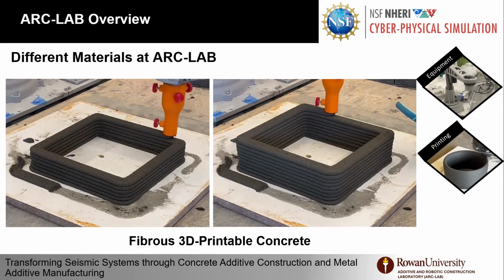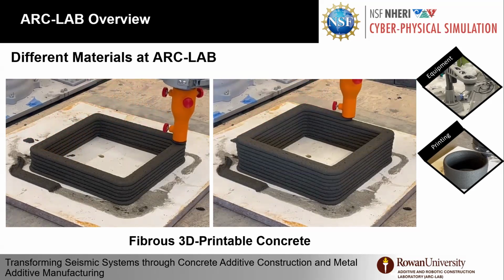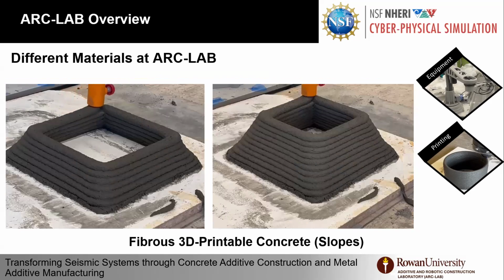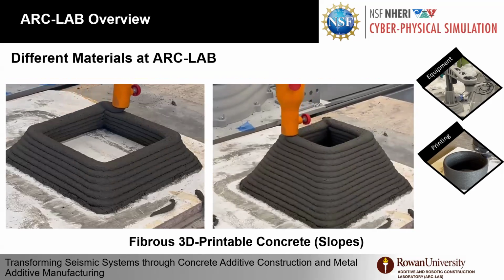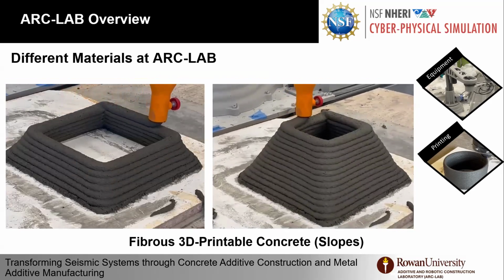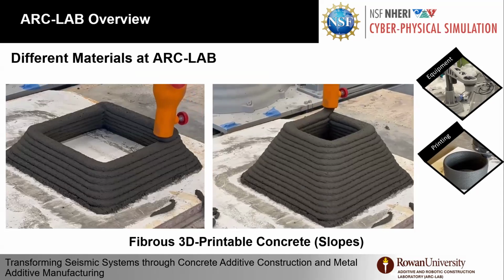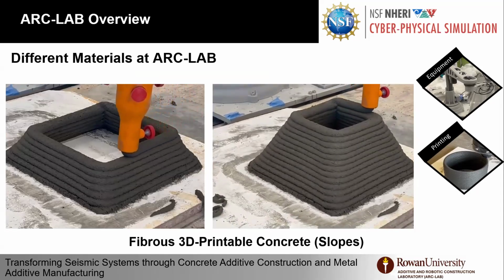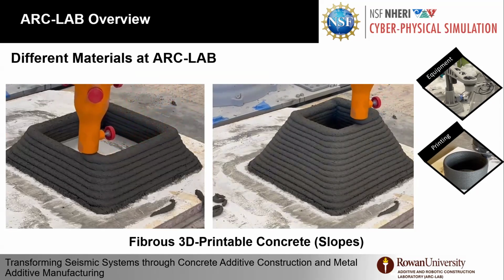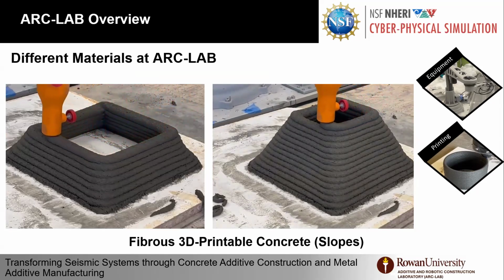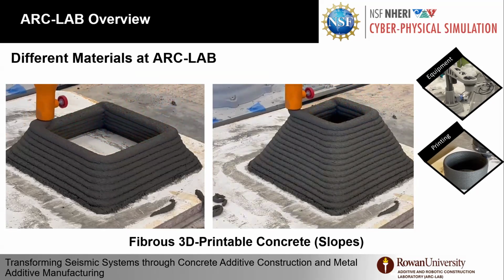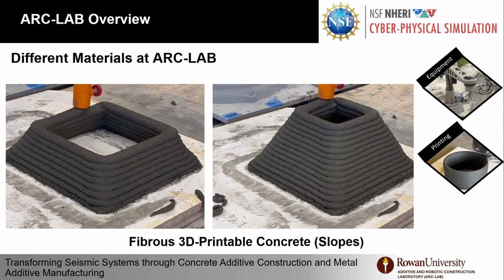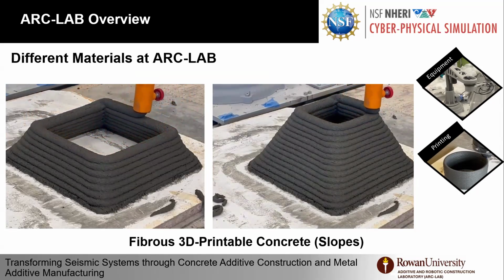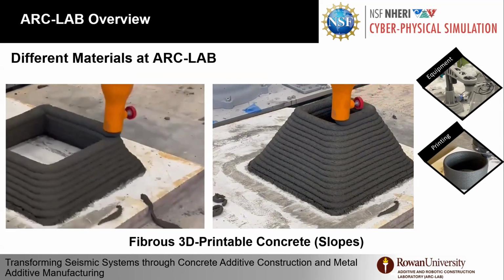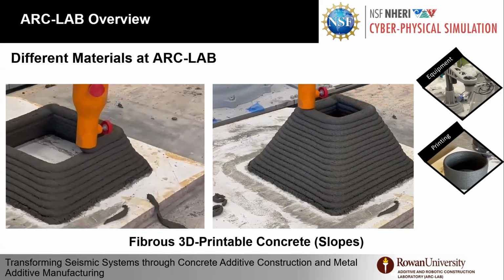We also take pride in the quality of our prints. We also print in slopes, and I'm going to mention why we're printing in slopes, because we claim that this method is fault-free, so we can now have the geometries. So here is a pyramid that we printed. It's a 12-inch by 12-inch pyramid that, as you can see here, was printed at a slope of around 26.5 degrees from the vertical position. And this one was actually printed with fibers too.